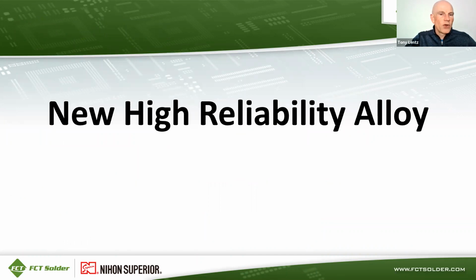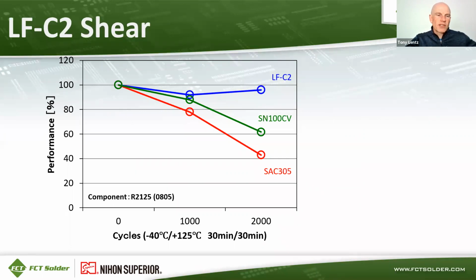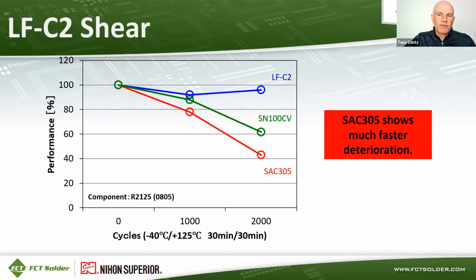So let's switch gears and talk about a new high reliability alloy that's being offered. Here's a performance measurement on the y-axis versus number of thermal cycles on the x-axis for a resistor component. The thermal cycle was -40 to 125C. LFC2 is this new alloy, which is the blue data. Then we've got SN100CV for comparison, which is the green data, and then SAC305 again is the baseline. You can see that LFC2 was much more stable in terms of shear performance throughout this thermal cycle test. And SAC305 showed much faster deterioration than either one of those other two alloys.